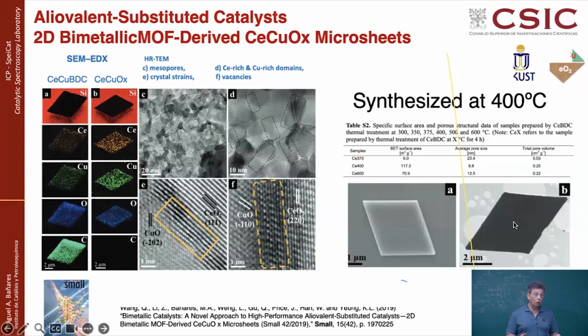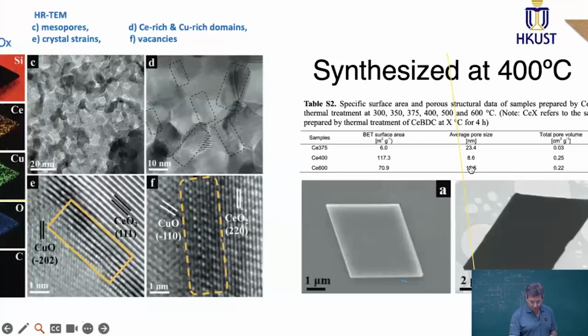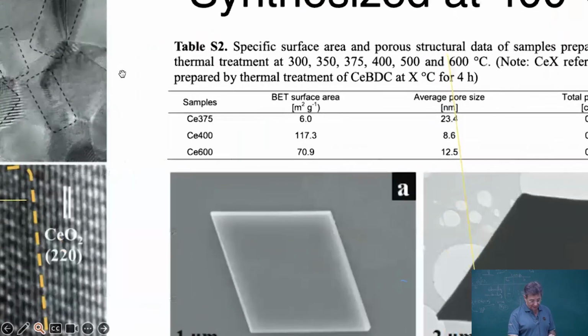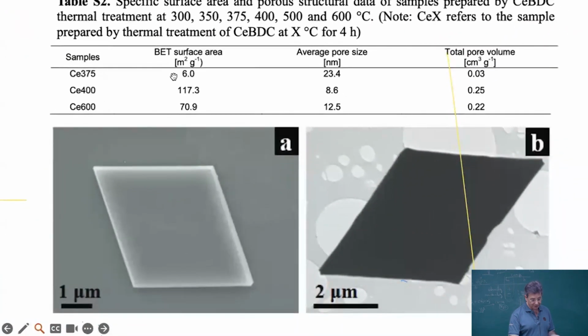When do you get the optimum mixed oxide? Well, you have to do several calcinations, and in our case, the optimum calcination temperature to get these porous oxides was about 400 degrees centigrade. If you were doing calcination of this material at 375, the surface area was 6 square meters per gram, which is not that much. At 600 degrees C, the area decreases to 70, which is not okay, but at 400, it's 100 plus square meters per gram, which is very nice.